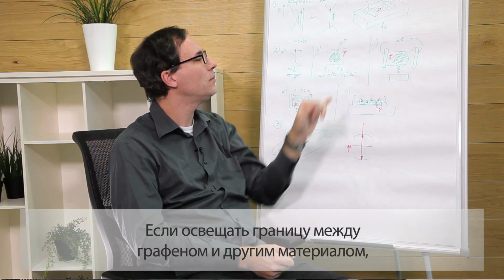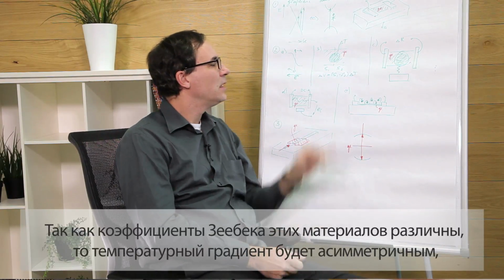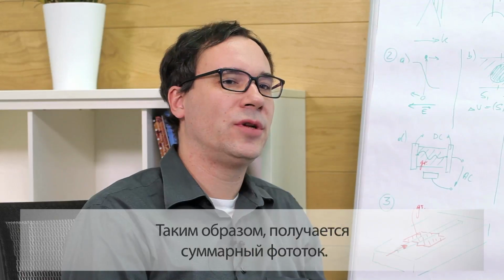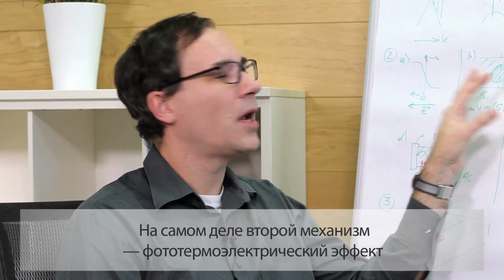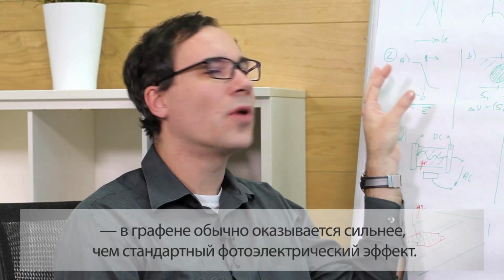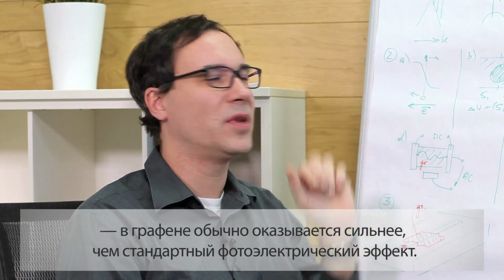One is the photothermoelectric effect, also called the Seebeck effect, where you again have an interface between graphene and some other material, and you shine your light at this interface. What you see then is that you heat your graphene sheet and the metal differently, so you get some temperature gradient there. As the Seebeck coefficients of these two materials are different, the current flow in both directions is not symmetric, and you generate a net photocurrent. In fact, it turns out that the second mechanism, the photothermoelectric effect, is usually stronger than the standard photoelectric effect in these materials.